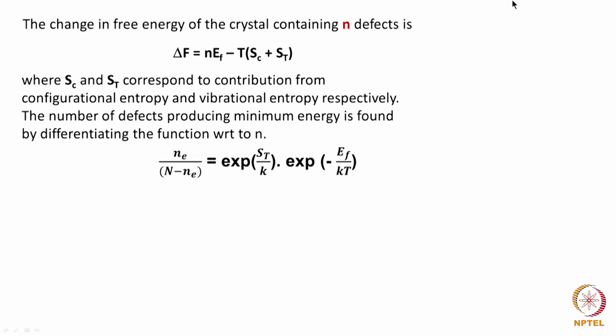Assume that by some means we are able to measure the vacancy concentration at different temperatures. Then we can get information about EF, and also about ST/k.